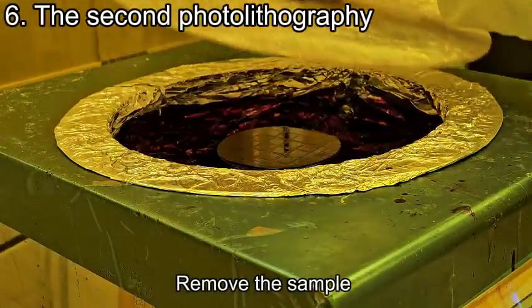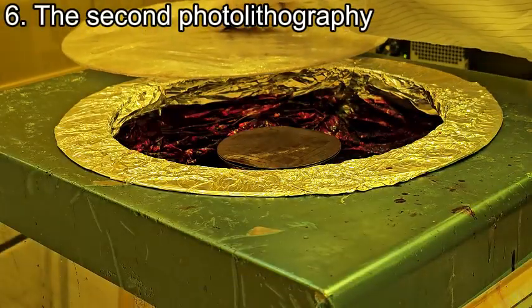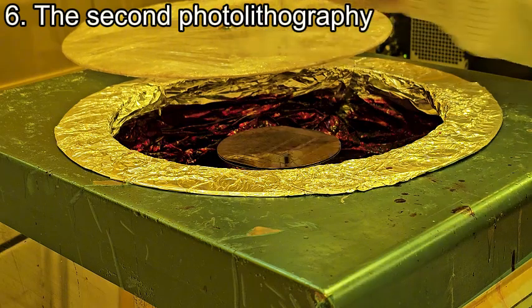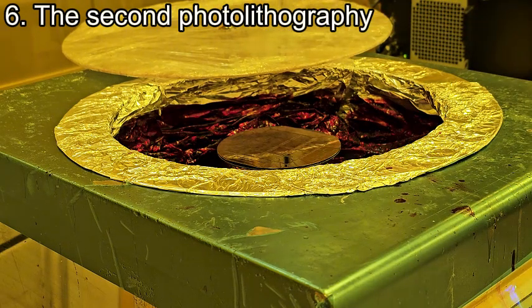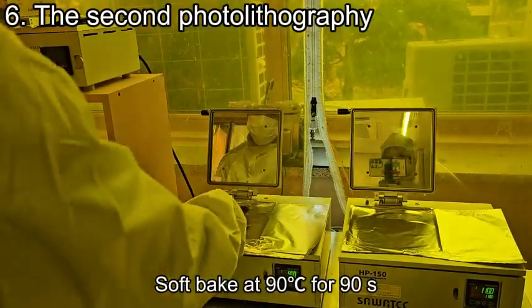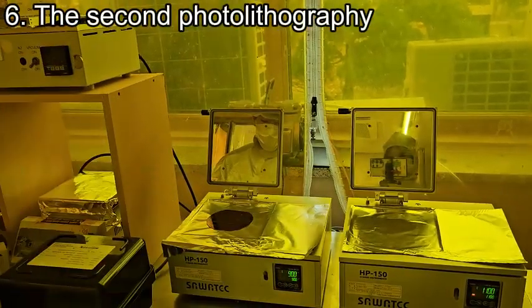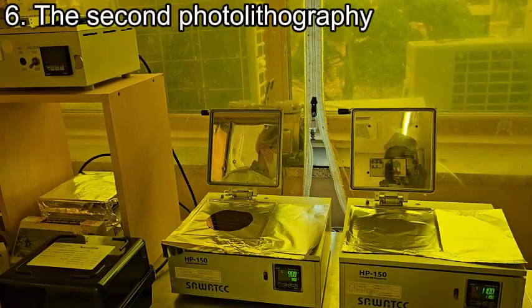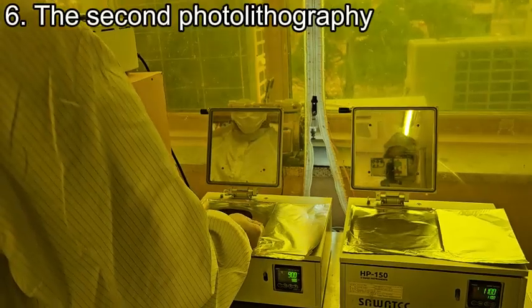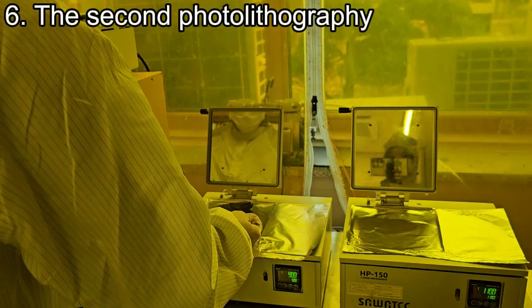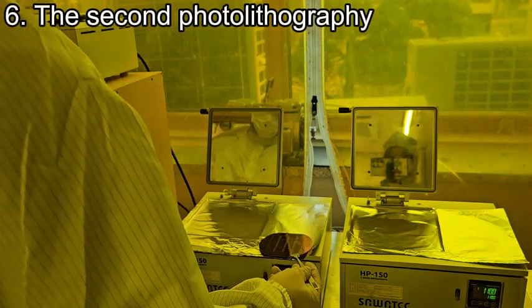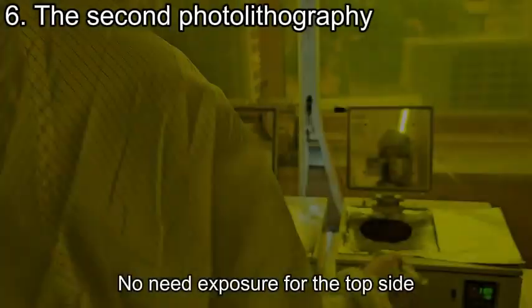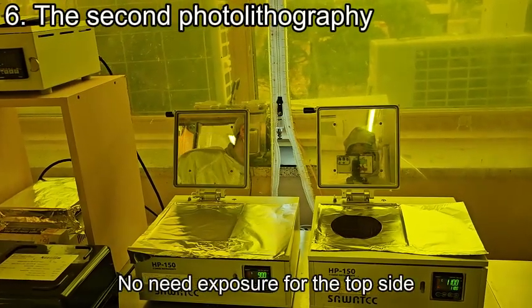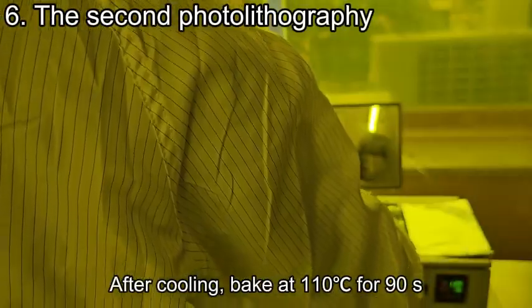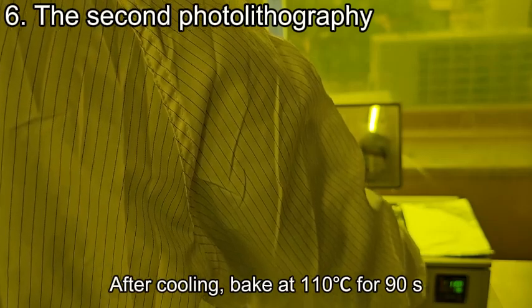Remove the sample. Soft bake at 90 degrees centigrade for 90 s. No need exposure for the top side. After cooling, bake at 110 degrees centigrade for 90 s.